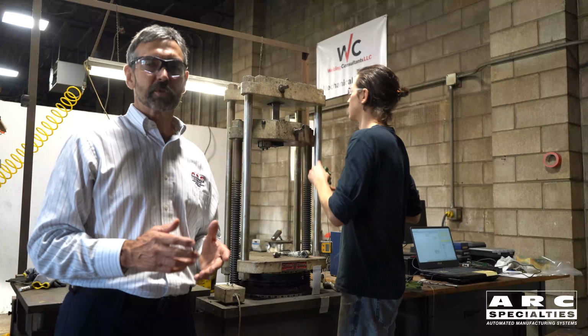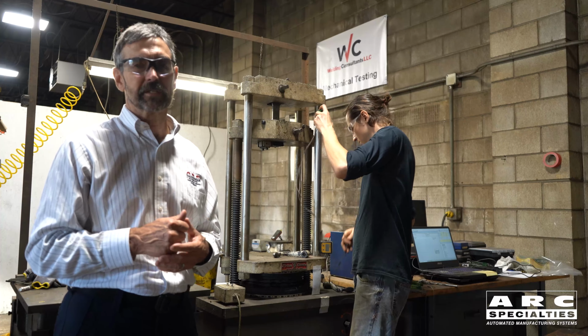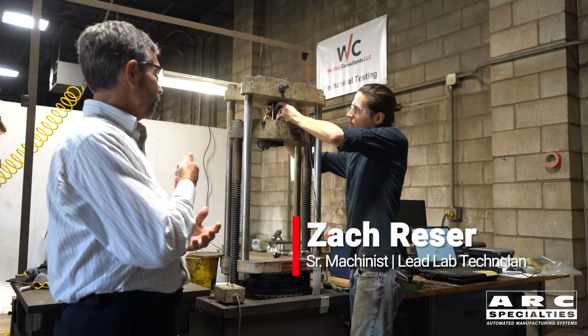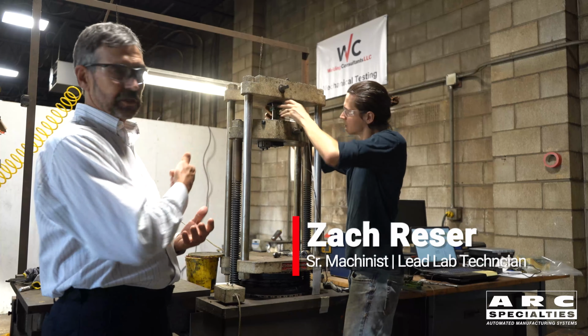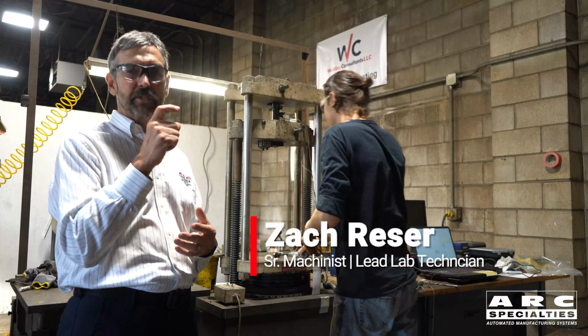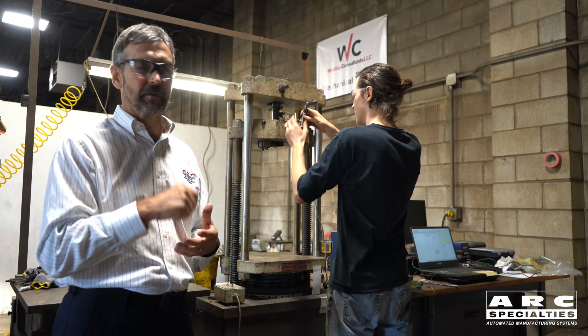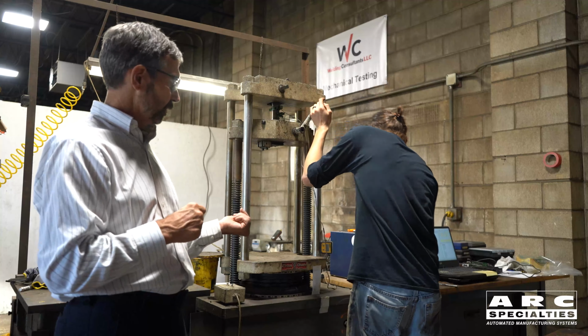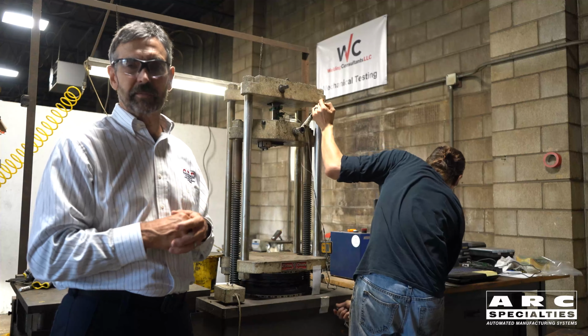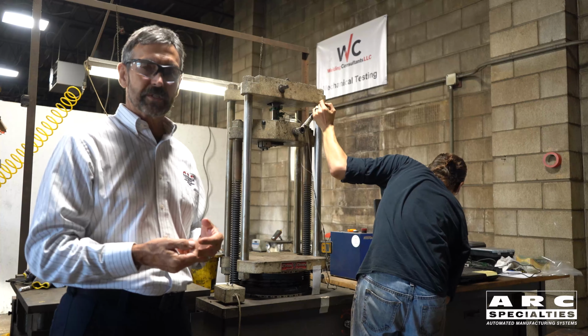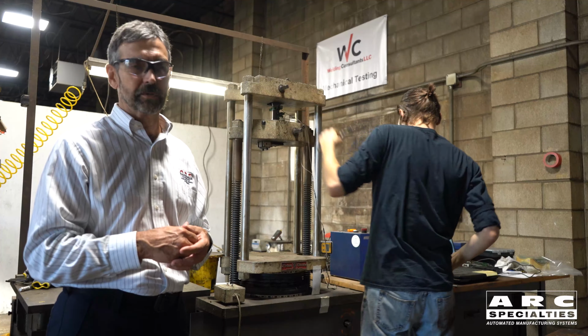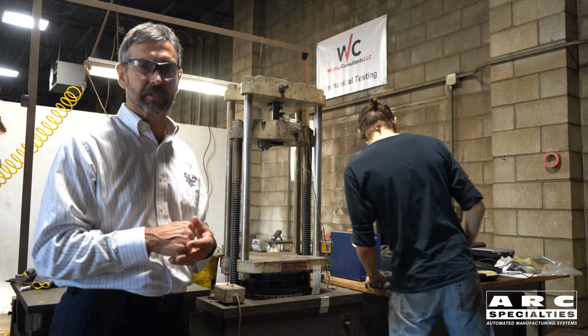So tensile testing is one of the most important destructive testing techniques. So Zach has cut and prepared these specimens. We clamp them into the machine. He's installing the extensometer, which actually measures the amount of strain or elongation in the part. Preloading the part now to get the extensometer preloaded. Then he'll zero this out. All this occurs before we do the actual tensile test.